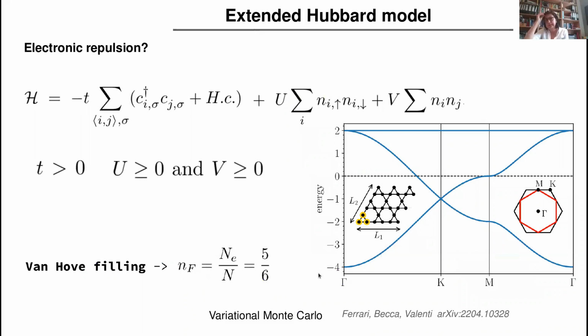So for that, what we did, we started first with this simpler model where we consider, let's first investigate the effects of electron repulsion. So our Hamiltonian is the kinetic energy, the Coulomb repulsion, and the nearest-neighbor Coulomb repulsion, and we situate ourselves exactly at the Van Hove filling. For the moment, I'm not putting the whole information of the system, only the fact that the filling in these materials is at a Van Hove singularity of vanadium d bands.